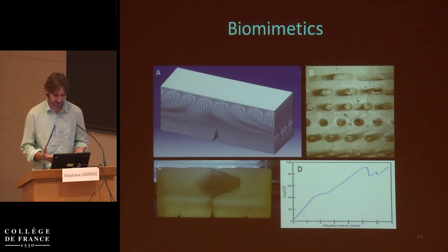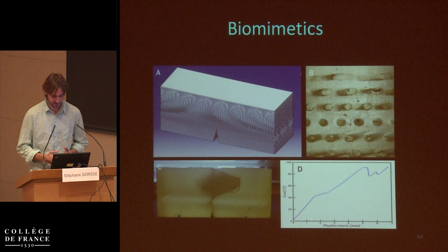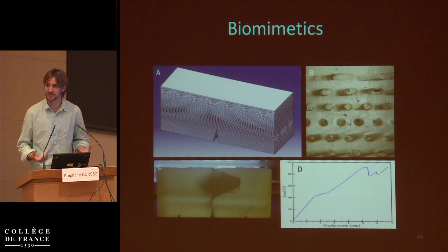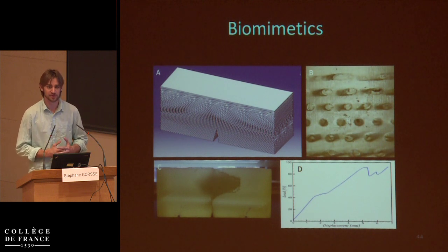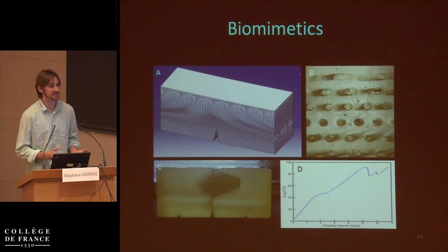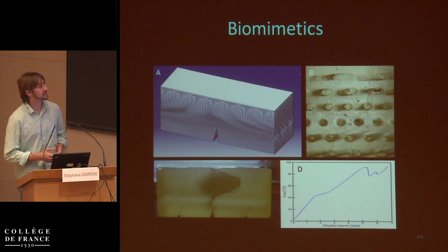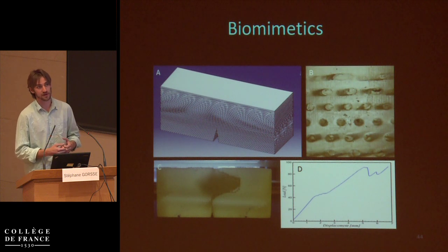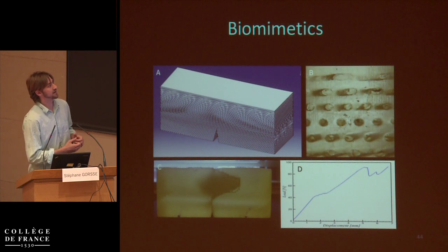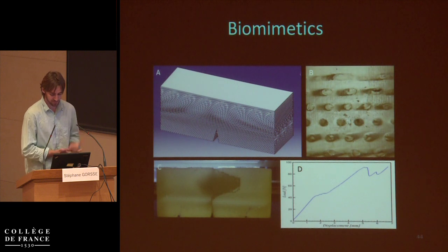we printed a helicoidal composite. And we didn't have access to a multi-material printer, but the support material was used as the matrix, and the actual intended-to-be-printed material was used as the fibers just to create a sufficient modulus mismatch. So this is obviously not mimetic, but it is at least indicative, or representative, of the structure at a very basic level.